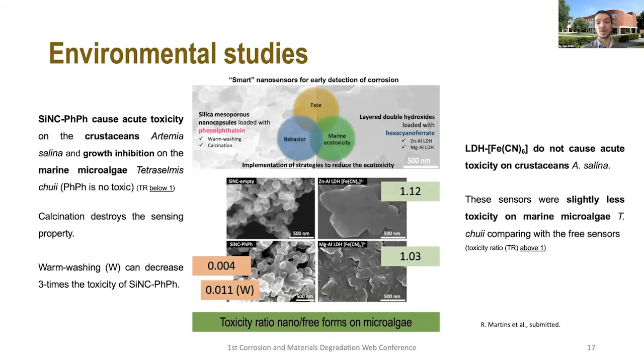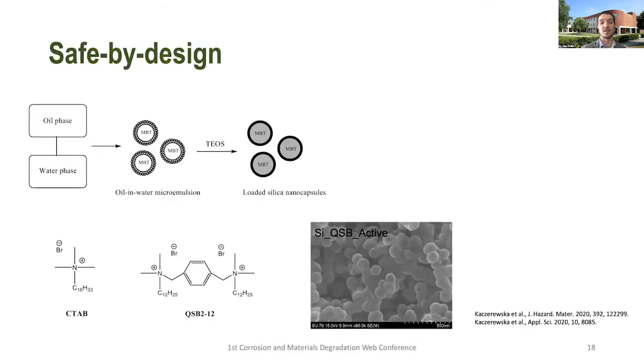So to introduce the last point of the presentation, we used this information to come back to the synthesis process and, using a safe-by-design strategy, see if we could change the material that we were using. So instead of using CTAB to stabilize the emulsion, this is an oil in water emulsion to encapsulate, here is the process for MBT, but it's similar for phenolphthalein, we tried to replace CTAB with a Gemini surfactant that we synthesized in the lab, which was found to be less toxic than CTAB. So we obtained the capsules, and here we can see an example of these silica nanocapsules obtained using another surfactant, and we were able to intercalate and immobilize this active compound, which was phenolphthalein.